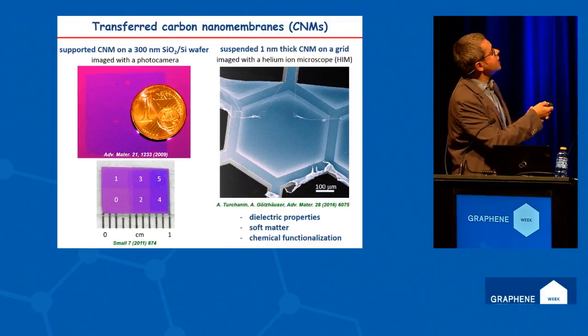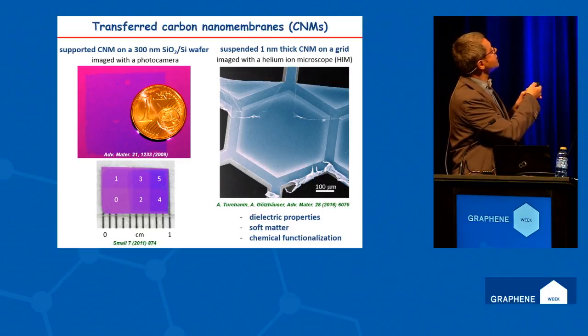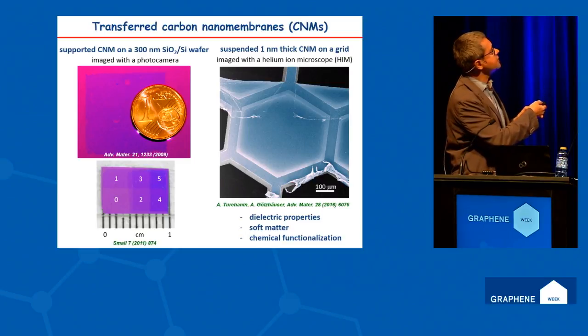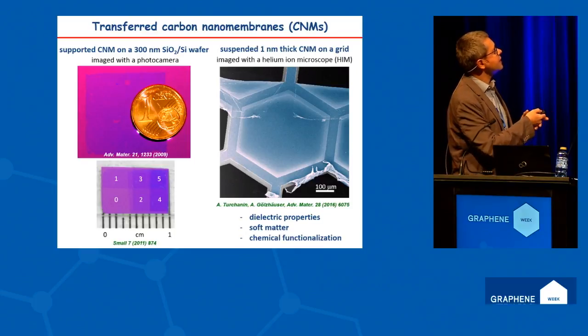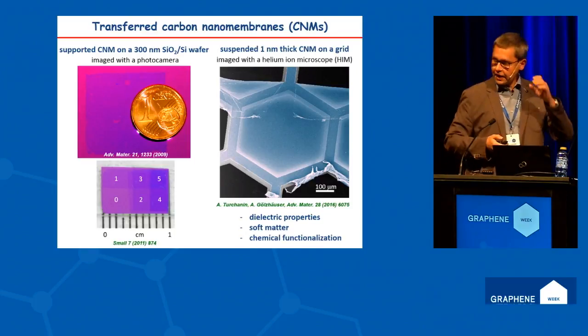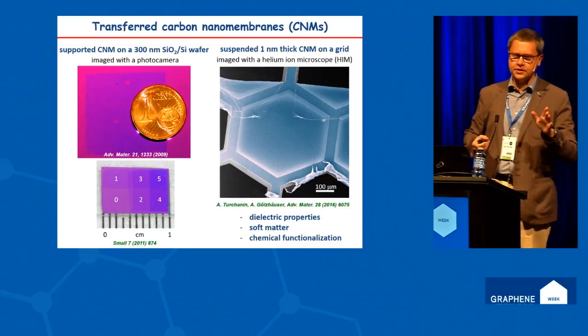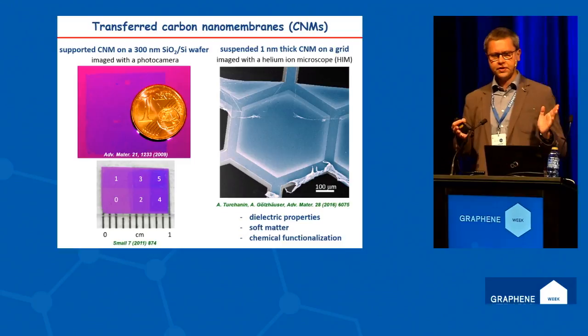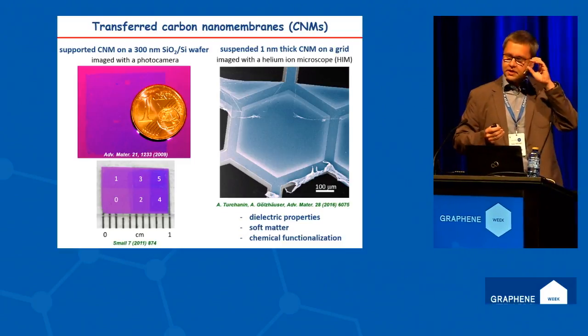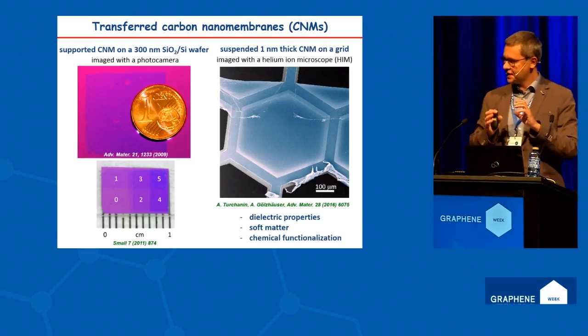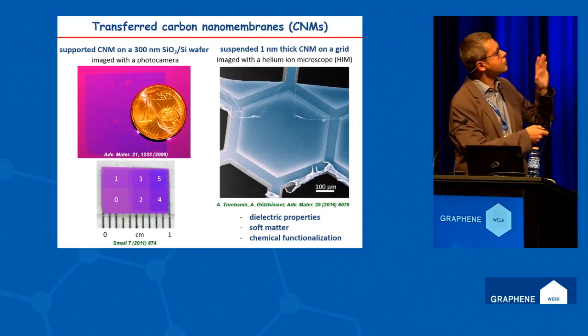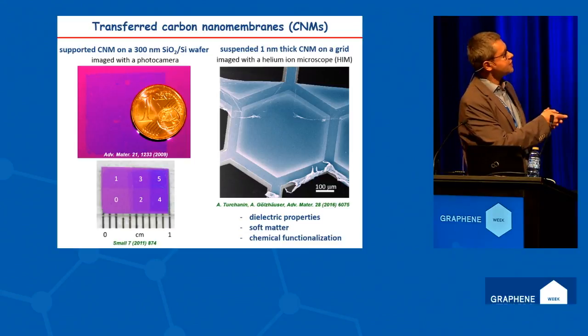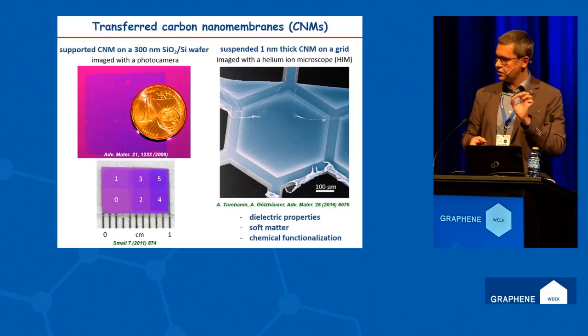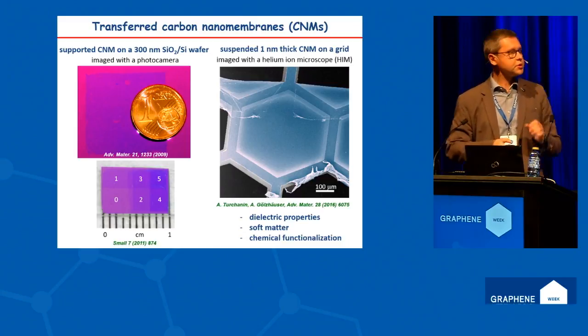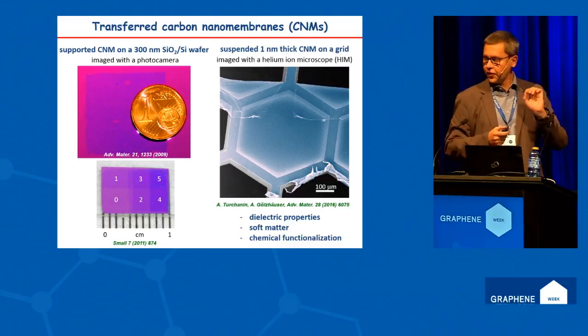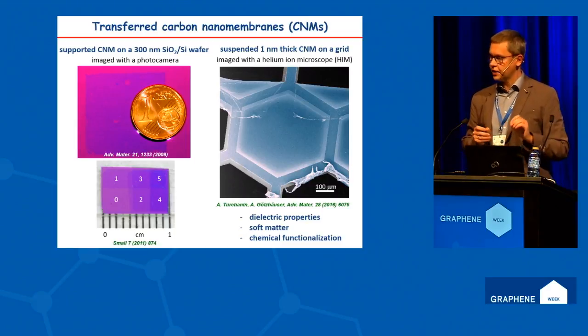The materials formed are shown here. This is an example of carbon nanomembranes on a solid substrate. You can stack these materials in thicker layers. You can make these materials freestanding. Actually, with these carbon nanomembranes, you can do any kind of microfabrication as you do with any other materials. I could speak about this for hours because it's a really interesting material. I would like to point out only three properties. This material is dielectric, this is soft matter, which makes it attractive for biological applications, and these materials can be perfectly chemically functionalized for the purpose of your experiment.